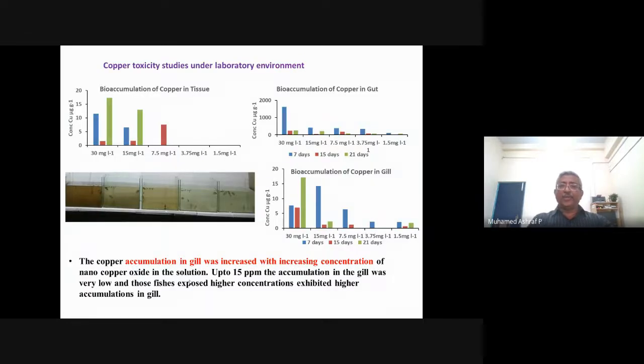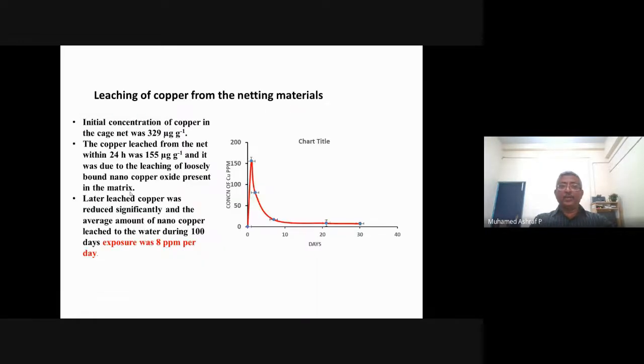And on copper toxicity, we also carried out a small study in the laboratory. It is a student's work, on the bioaccumulation of copper in tissues, in the gut, and in the gill. Because we are using a very high amount of nanomaterial, based on that concentration we found an increase, but as such it is not much accumulation. Only accumulation in the gill increased with increasing concentration. In other places it is not so, because they are living in an environment of highly concentrated copper and nano copper oxide water.